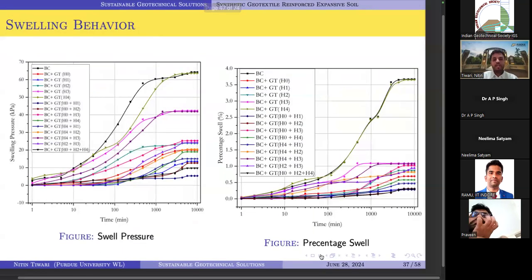Okay, so let's talk about the results directly. Initially, the swelling pressure of our soil was around 60 to 70 kPa. And you can see with the different depth combinations, H naught, H, most of our samples go to less than 10, 15, or even if you see most of them, they are less than 20 kPa. So from 80 to 20 kPa we reduce.